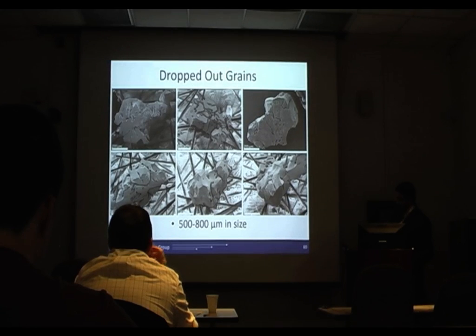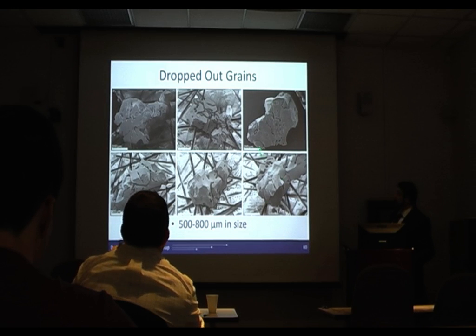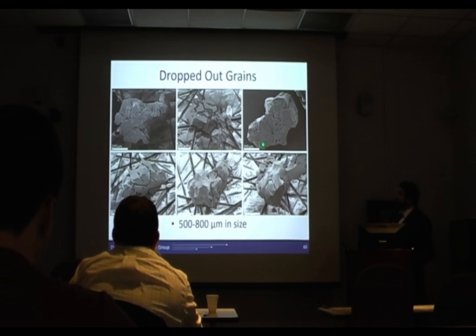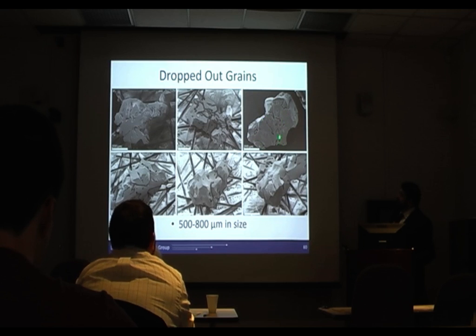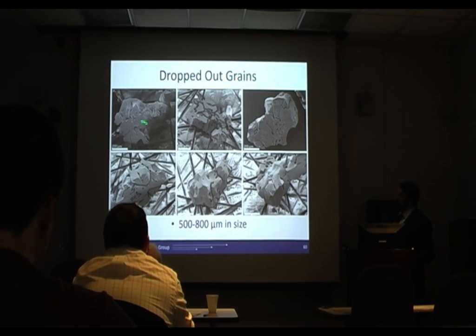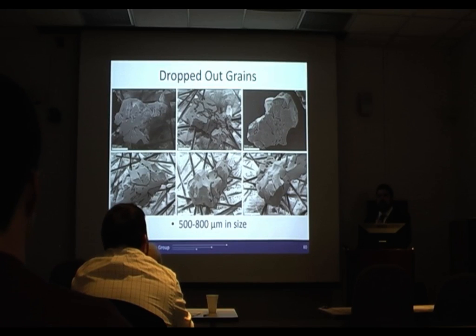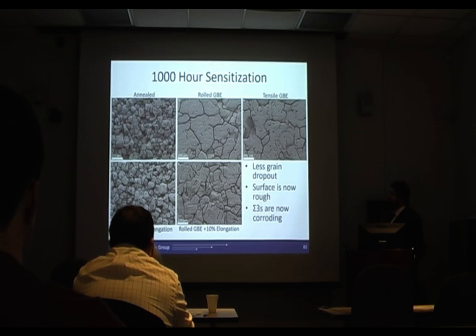And then on slide 60, we see that these are actually 500 to 800 micrometers now dropping out of the GBE microstructure. And you can see this is actually a flat face. Almost all the grains have a very obviously flat face. So this is the polished surface of the sample, so it's still our surface layer that's dropping out. And then when we look at the 1000 hour, in the previous conditions, the polished surface looks pretty similar.